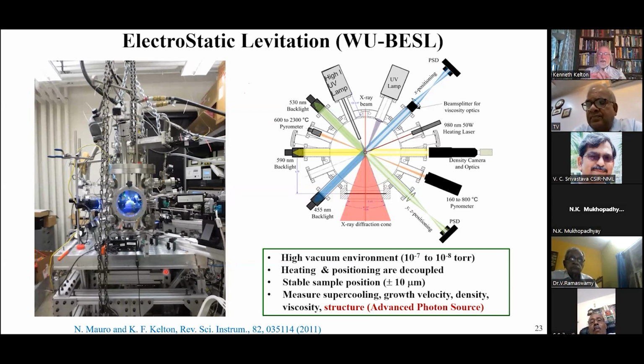When we put a metallic sample in there, we end up getting charge separation because of the very high voltage on the top electrode and bottom electrode. And so that causes the sample to be levitated. We then look at a high intensity LED, which is what you see here, and we look at the shadow of the sample on something called a position sensitive detector. We have two of these that are at right angles. They're orthogonal to each other. And so from the shadow, we know exactly where the sample is sitting, the X, Y, and Z coordinates.